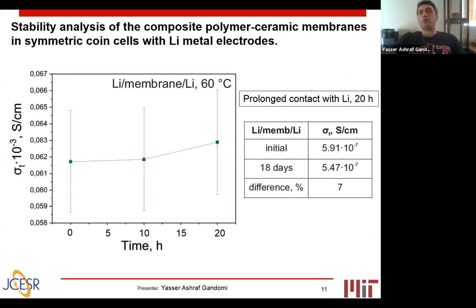The first step was to look at their stability within the coin cells in the solid state. These experiments have been done in coin cells, sandwiching the composite membranes between the lithium anode and the cathode. We looked at their stability at 60 degrees C and also room temperature for extended days. As you can see here, they maintained their stability throughout the entire experiment, which was very encouraging.